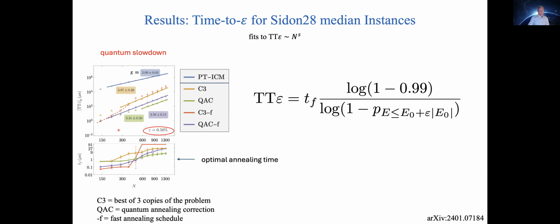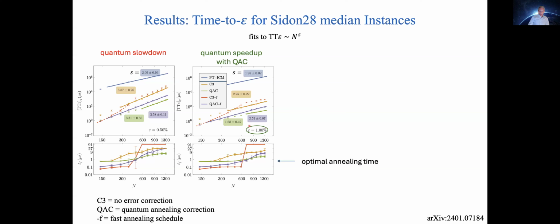So there's no quantum advantage. There's a quantum slowdown. So PT-ICM wins in this case. But as we increase the optimality gap to 1%, now we see that the QAC strategy in green has a slope of 1.68 versus 1.95. So it's actually better. Not true yet for the C3 strategy or the fast QAC. So here we already have an advantage, a quantum speedup with QAC.